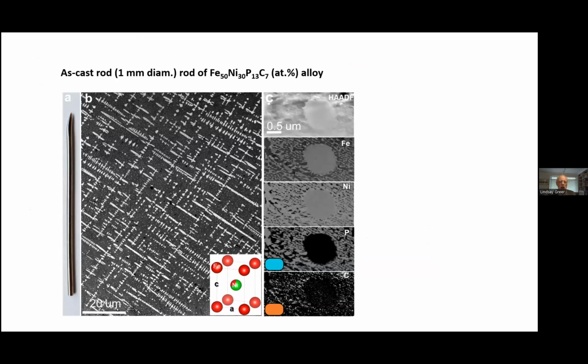This is our work. In the classic way of science, we were looking for something totally different. We didn't have magnets in mind at all. We were looking at an iron-nickel-based alloy, but we were interested in the possibility of whether this alloy could avoid crystallization altogether. So you wouldn't have a crystal structure, you would have a glass. Well, we did not succeed.